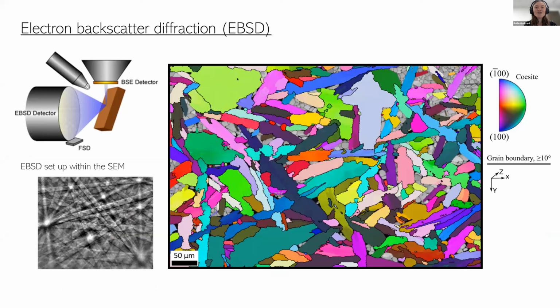So the next technique we're using is an electron-based technique, which is EBSD. It was mentioned earlier. This is where you fire electrons at the sample that's tilted at an angle. They go into the sample, they diffract out, and then you collect those patterns on a phosphor screen, and you get these diffraction patterns for every single point in your grain. And they give you an idea of not only which phase you're looking at, but also the orientation of every point within the grain.